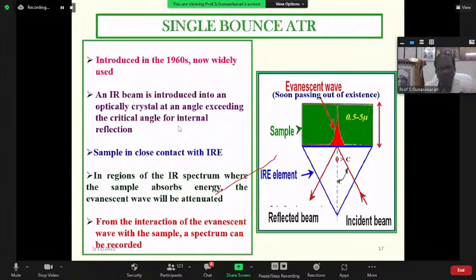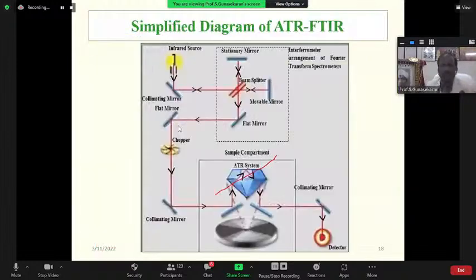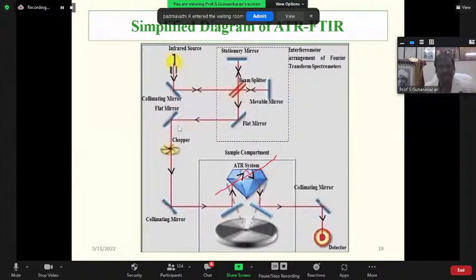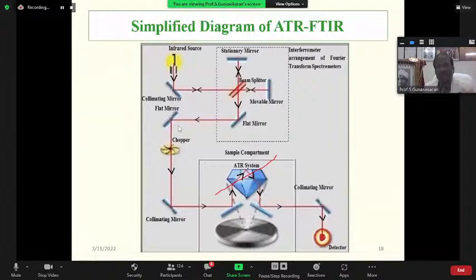The sample preparation is minimal. You put the sample and get the spectrum within 32 seconds. If you use the KBr method, you have to spend at least 25 minutes in the laboratory only for sampling. But in the ATR technique, 32 seconds is more than sufficient. We can get the spectrum immediately. This is the advantage. So the transmittance sample compartment is replaced by an ATR accessory like this. This is a diamond crystal, in a simple way.